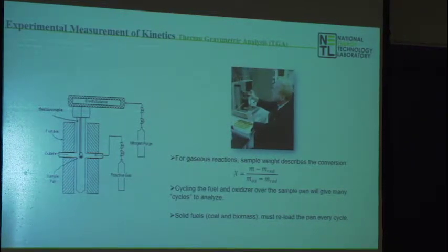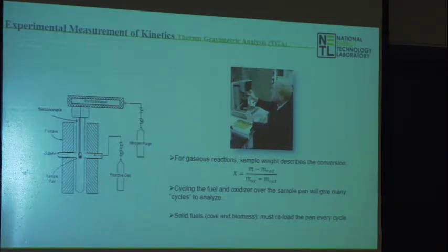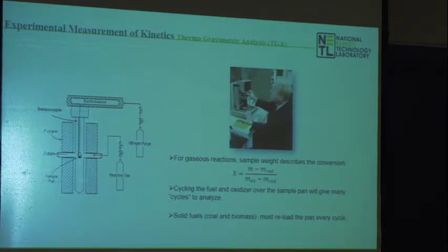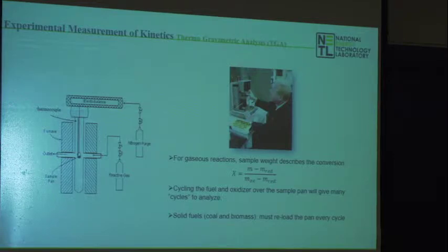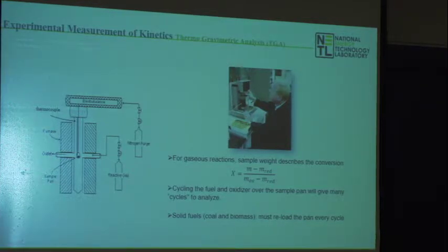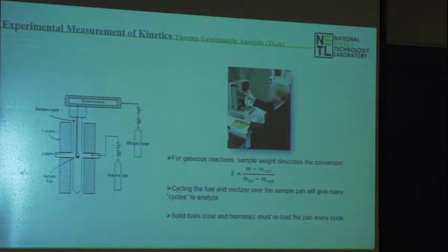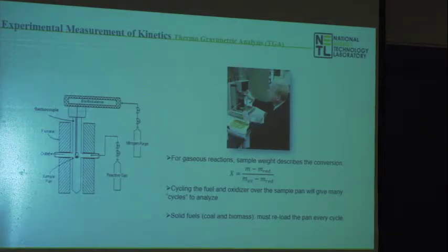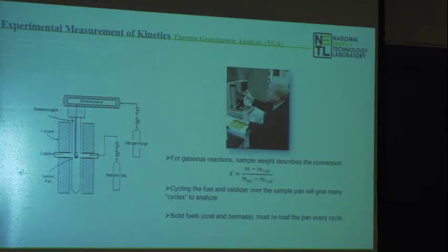Does that make sense? You put it in there, it's sitting in there, maybe starting in the oxide state. You put fuel in it, and it starts to release the oxygen, and then the weight is being reduced as that oxygen comes off. You're measuring that, and so you're measuring the rate that that material is being reduced. As soon as it reduces fully, you can introduce oxygen, and the weight will start to go up again, right? And you can measure that rate as well. So that's how you get the kinetics out. Very straightforward for gaseous fuels.